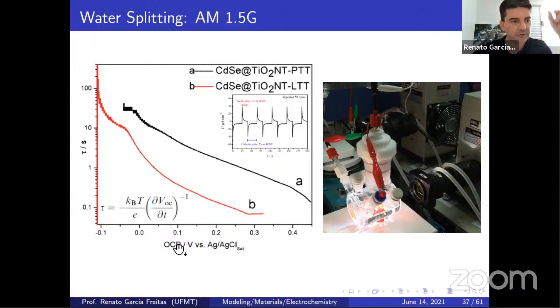Why this one? If you take a look here, the open circuit voltage decay is, if your device is illuminated, we have all the electrons in the conduction band, isn't it? And if we turn off the light, the electrons recombine to the valence band. So the lifetime here is higher, and here we have a lower lifetime. The lifetime is higher for the previous thermal treatment compared to the later thermal treatment.